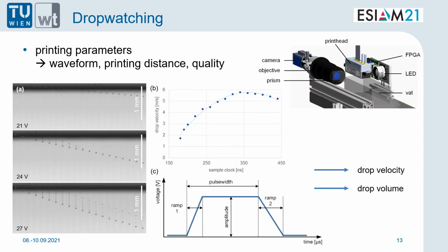For the studies, we included two different printheads in the system, different in drop volume, resolution, and temperature. To evaluate the necessary printing parameters for the inks, we also integrated a drop watching system, which is an advanced stroboscope to check the drop's behavior in flight. Increasing voltage and pulse width increases the drop's velocity and therefore the optimal printing distance. A too high velocity, however, increases the possibility of so-called satellite drops and therefore loss of resolution. Finding the acoustic optimum, which is here, for each ink and printhead has priority in material testing.